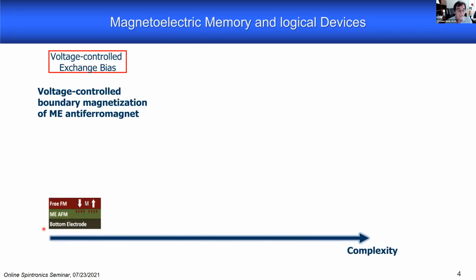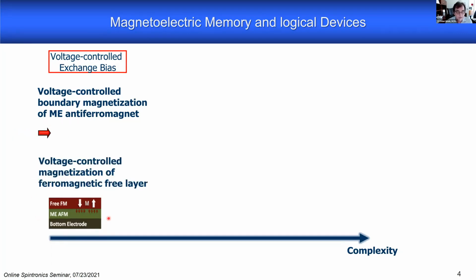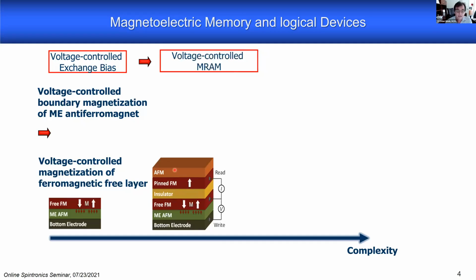So this is basically a fundamental building block here, this voltage controlled exchange bias system, where you have this voltage controlled boundary magnetization. Then it takes just one more element to make a magnetic random access memory out of it, so to say. You can put a tunneling magnetoresistance structure on top. So you have this free layer, which you can now read out by bringing it into this tunnel magnetoresistance structure. For this, you have to drive a current through the system to read out the contrast in the tunneling magnetoresistance. But the writing of the bit information is pure voltage-driven writing.